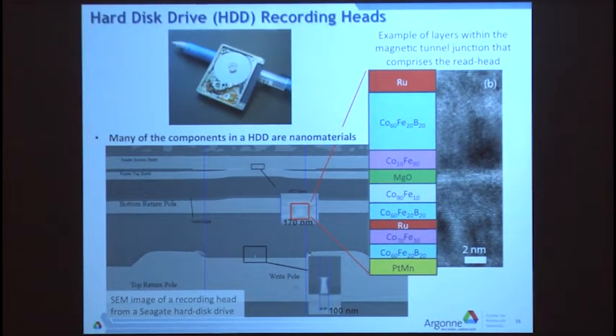It turns out that a very important thing to control is how these layers behave and what happens when you heat them up, which is one thing you have to do to make the structure. In this case, this is actually a Seagate head, but we were looking at this with a company in Japan, Canon Anelva, that make the big pieces of apparatus that are used to grow these structures. If you look here, the platinum manganese, then 2 layers, then ruthenium, then 2 magnetic layers, magnesium oxide, 2 magnetic layers. That's a very complicated structure. Why would they even bother with that? Why not just use 1 magnetic layer in each case?